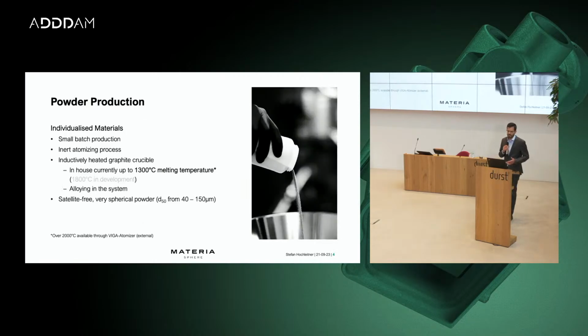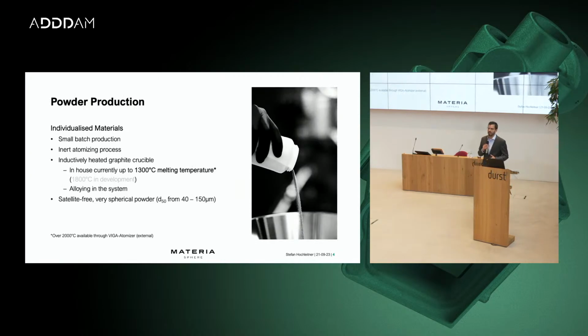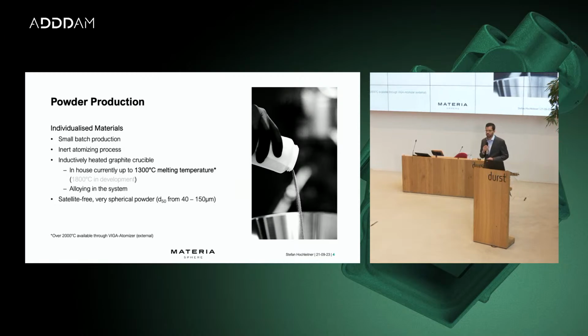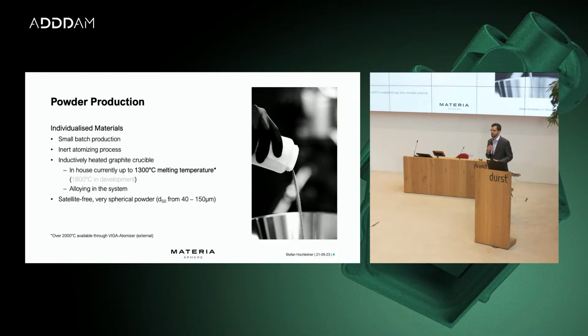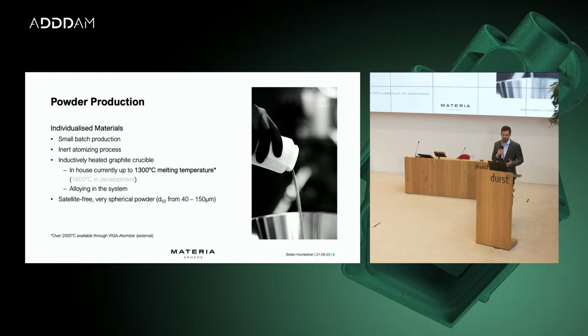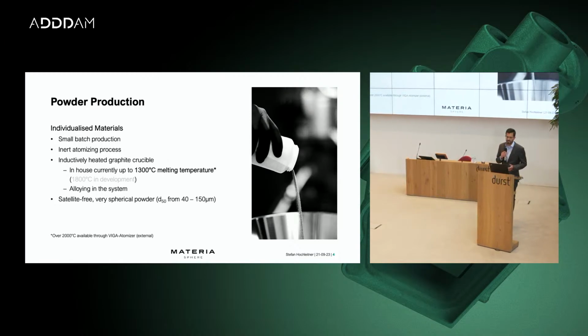So what's the first and biggest enabler for our work? It's the powder production itself. We focused on getting machines that can help us with individualized materials, and therefore we use a small batched production machine which uses an inert atomizing process. We use an inductively heated graphite crucible, so it's possible for us to alloy directly in the system. And the outcome of the machine is very spherical, satellite-free powder with a D50 particle size distribution from, let's say, 40 to 150 micrometers, depending on the customer's needs.